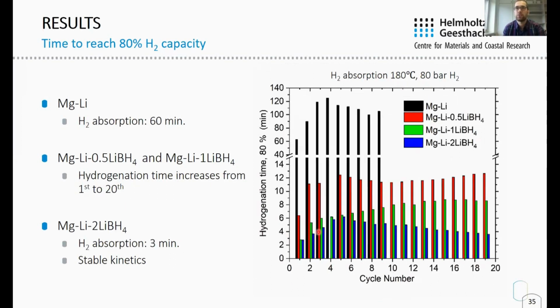In the case of hydrogenation, the pristine sample absorbs 80% within 60 minutes. All lithium borohydride containing samples absorb hydrogen very fast. However, we have the same trend as before. Only the sample containing 2 mole additive has stable kinetics with absorption times around 3 minutes.